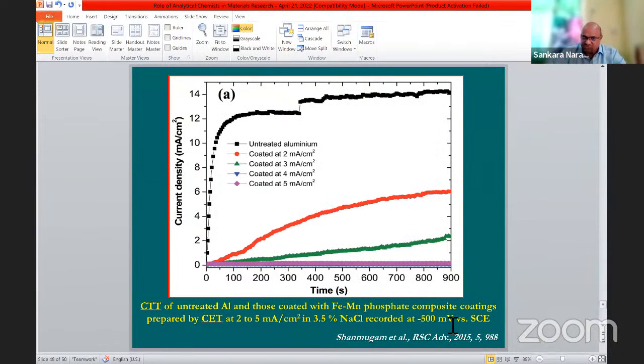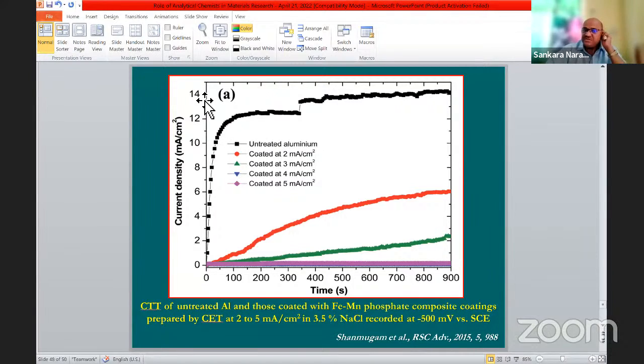You increase towards the anodic side. Automatically, there will be an increase in current also. Here it is only 6 milliampere per centimeter square. Here, up to 14 milliampere per centimeter square. And the rest, that you could distinguish among the material coated as a function of current density. Even here it is 4 and 5. It is not that much distinguishable. It's about the same.